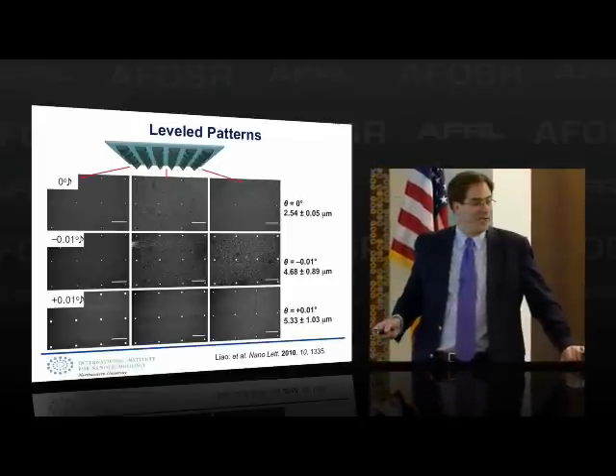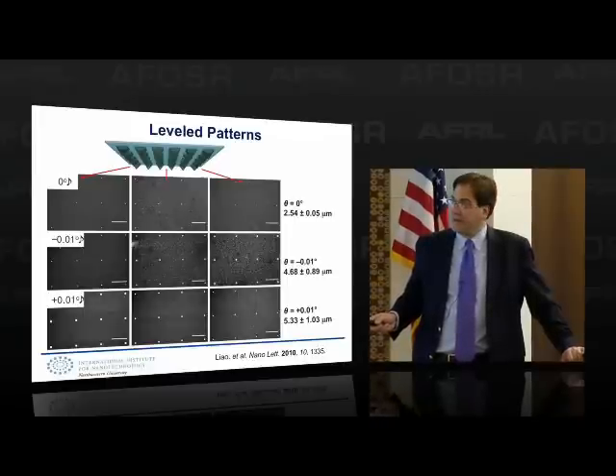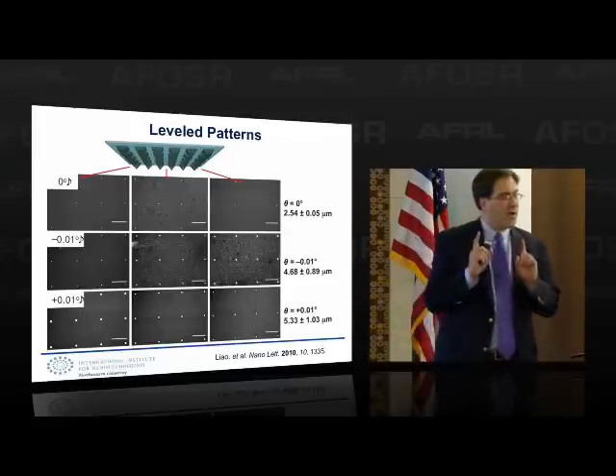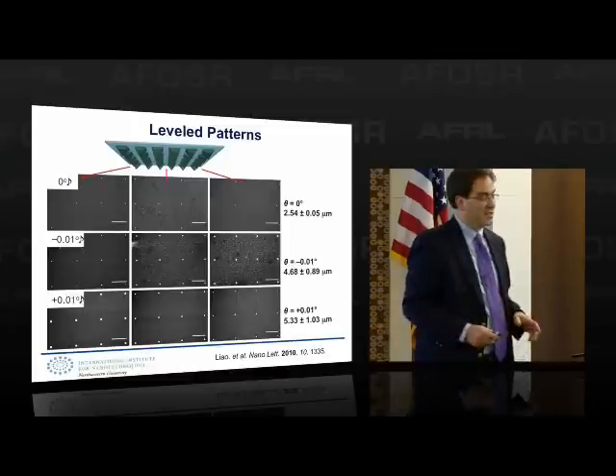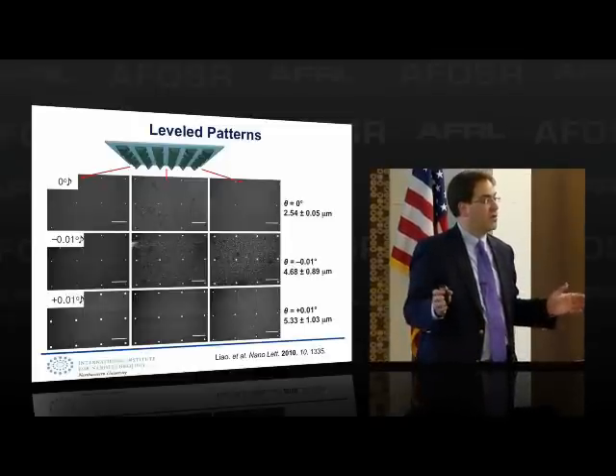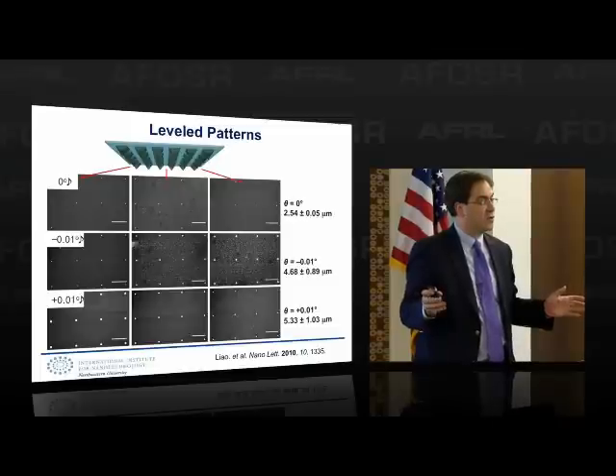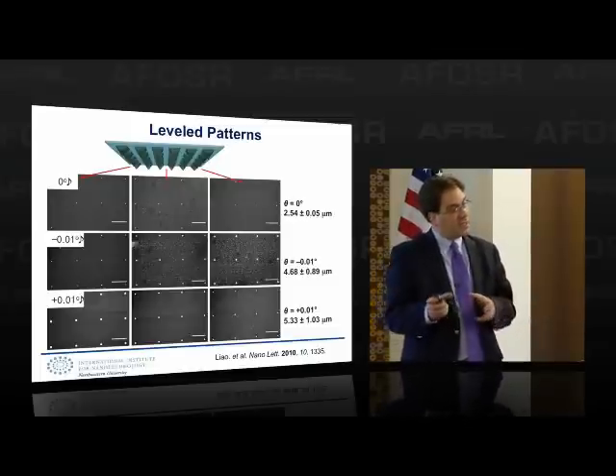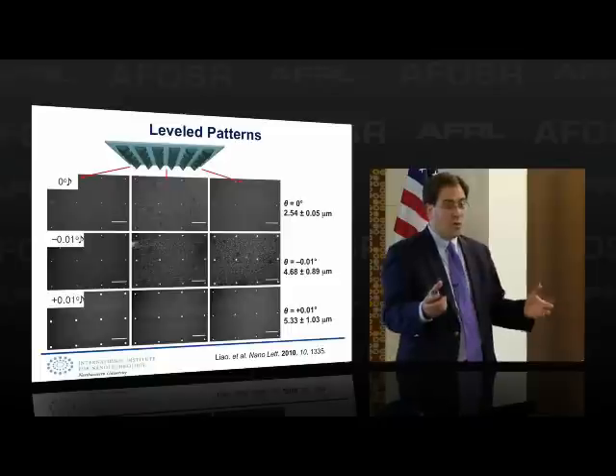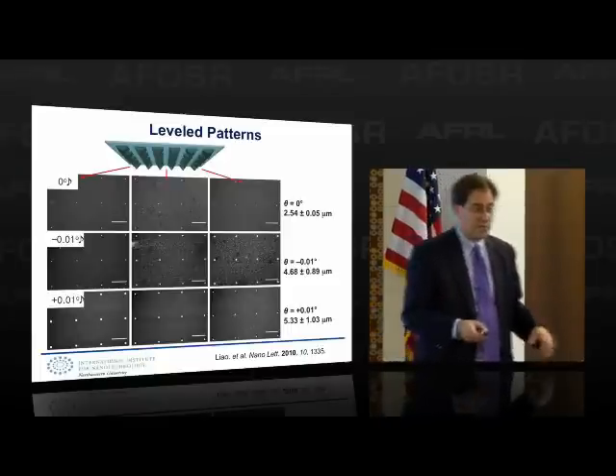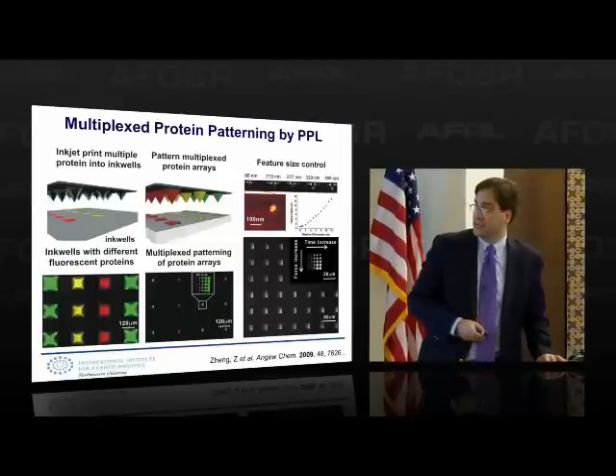Here's why you have to be so good. 1/100 of a degree, right? Look what happens. Small, medium, large. So we're pushing harder on this side, right? And less so as we go across here. Flip it around, large, medium, small. And so if you're off by 1/100 of a degree in terms of theta in this case, that's going to kill your whole experiment if you're trying to make many features of the same size over large areas. But now what I can do is literally use this as a way to quantify and figure out when the array is level and when I'm ready to go make these structures.